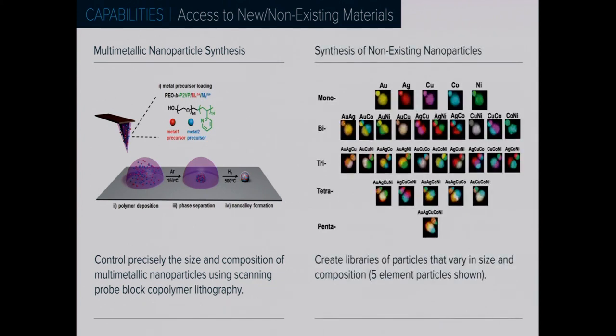So we wanted to prove something, and so recently we just published this in Science Magazine. We said, let's go take 5 elements. Nobody's ever done this before. And let's ask if we can use this technique to make every combination of them. First, the pure structures. So each of these are particles, pure gold, pure silver, pure copper, pure cobalt, pure nickel. They're cartoons in the upper left. This is what we call an EDAX image. It's a technique that allows you to get an elemental map of what you produce. So you can see they're all one color because they're all one element.